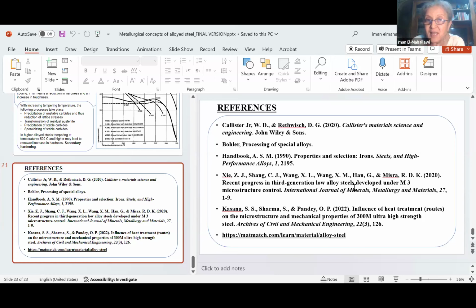So this is the idea here, that we control the properties so that we would have hardening phases. We know the hardening phases are the martensite and the bainite, and if we can control a microstructure which contains not only ferrite and pearlite, or not only martensite, because ferrite and pearlite on their own would not be very strong, and martensite is not tough. So if we can control the microstructure to contain more than one microstructure, you will benefit from both. And that's the idea behind the TRIP and the TWIP, which are actually developed for the automotive industry for having higher strength combined with higher toughness or ductility.